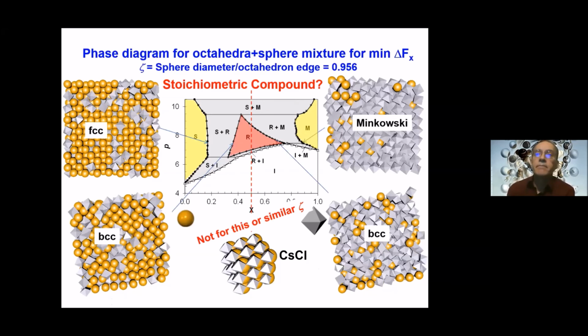Well, how did you recognize that it was appearing? You've just got atoms in a box. And so you have to count the atoms somehow, or the distances between them, or something. Yeah, I think that the first indication was that when the phase became, say, non-isotropic, when we were doing this mapping over here, the integration was going haywire. So there was something about the property of the phase, the density, and it's a semi-grand canonical ensemble. So there was also something about the composition, so things were changing in a discontinuous way. So that forced us to re-examine whether it was just some issue with the simulation, or what's happening with the phases.